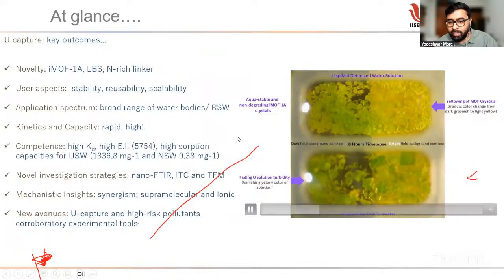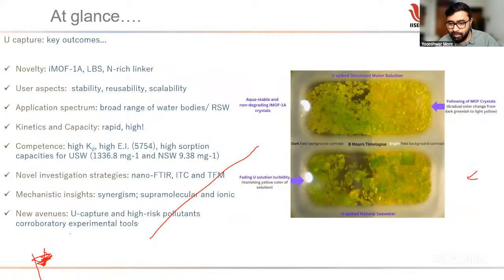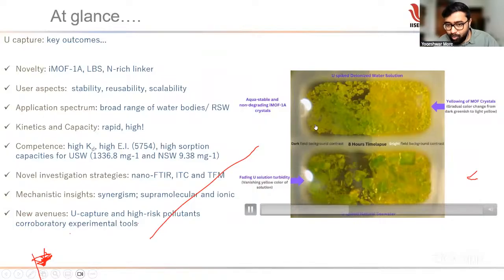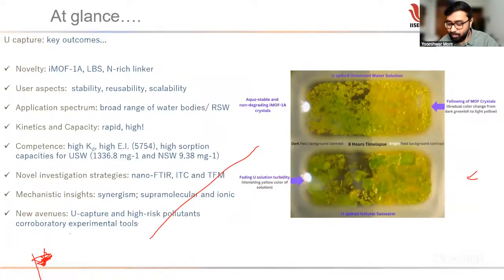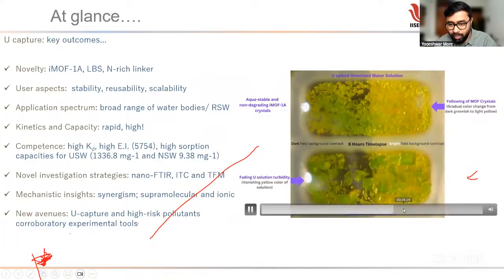This is the overall 8 hours of time lapse we have collected in a confocal microscope with the control time frame. What it shows: these are the MOF crystals and the dilute uranium solution. They are not only changing the color, but the MOF crystal is not undergoing degradation, because we are going to put it in real-time seawater. If the MOF crystal degrades, then we cannot reuse it. So this video shows particularly how MOF stability isn't affected, but uranium is being adsorbed.